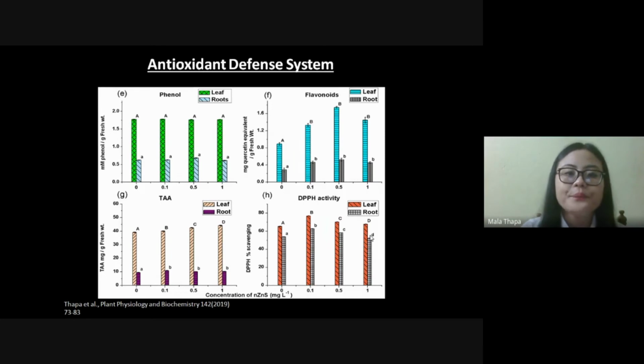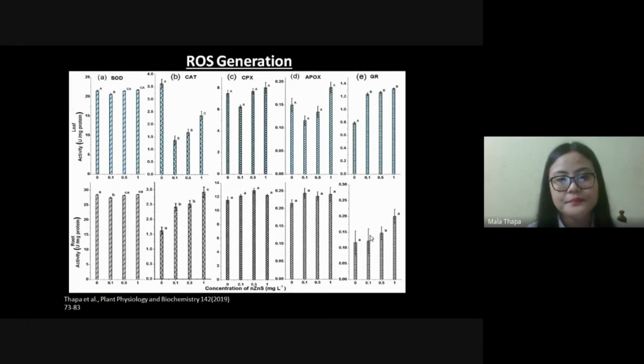Now, role of zinc sulfide in antioxidant defense system. In our study, we did not find any change in phenol content, whereas there were significant increases found in flavonoids content, total antioxidant activity content, DPPH activity content. The increase was in dose-dependent manner, which indicated the antioxidant attribute of zinc sulfide nanoparticle.